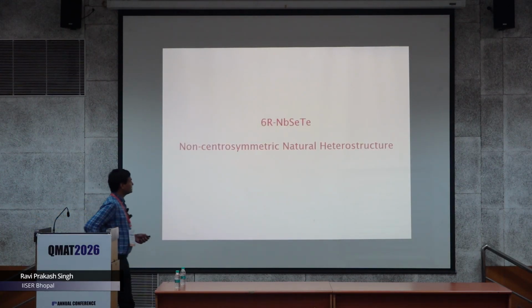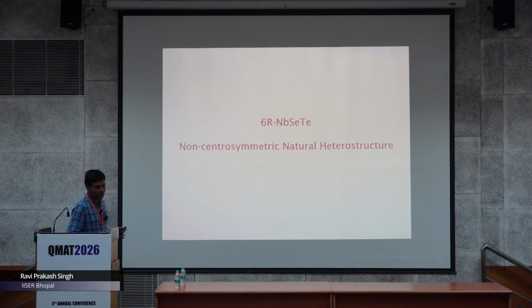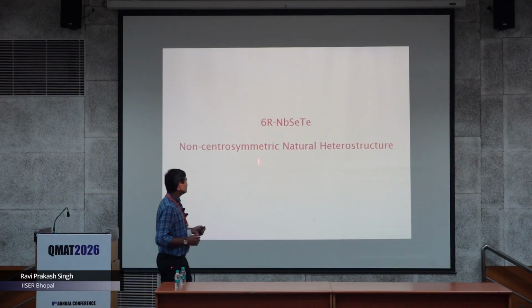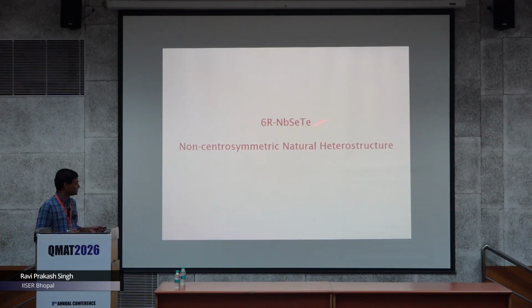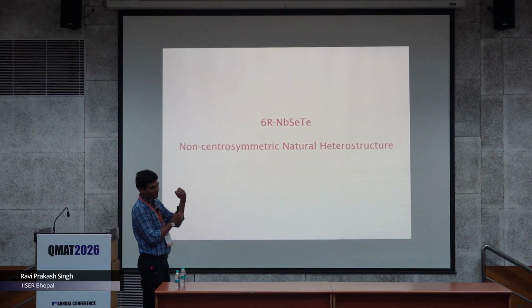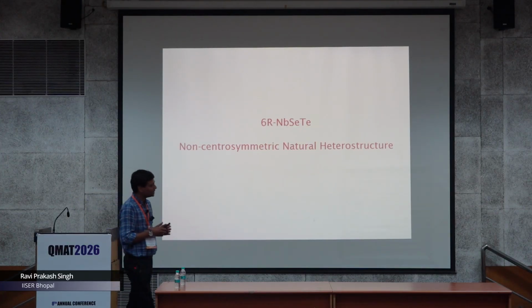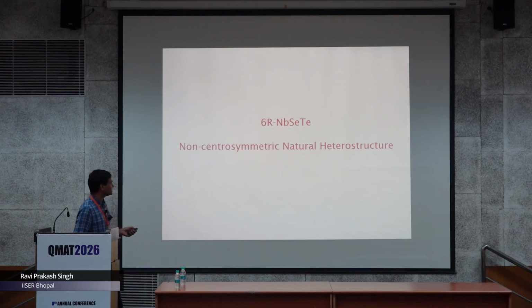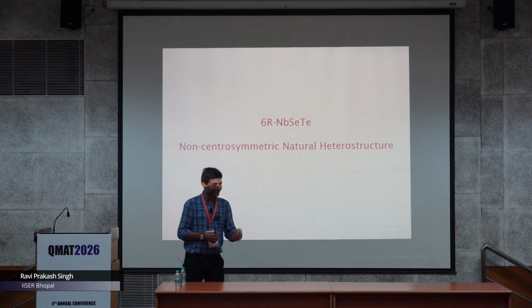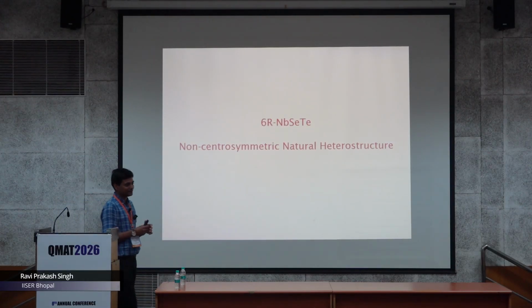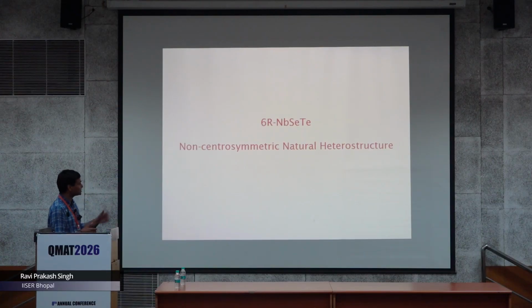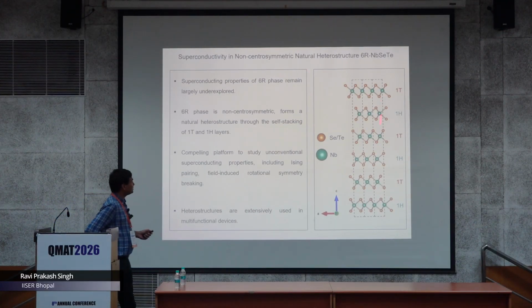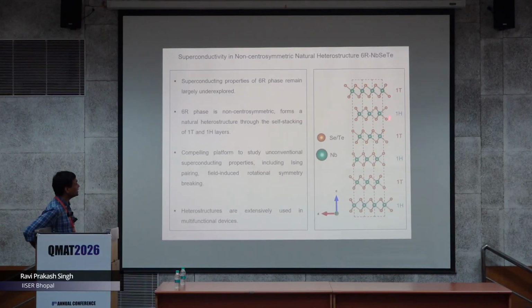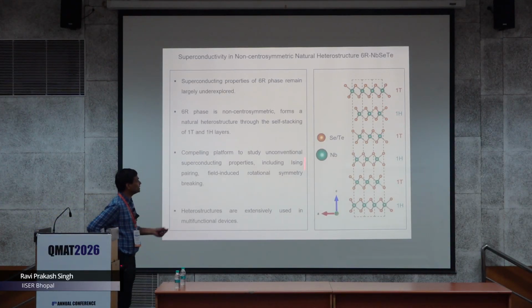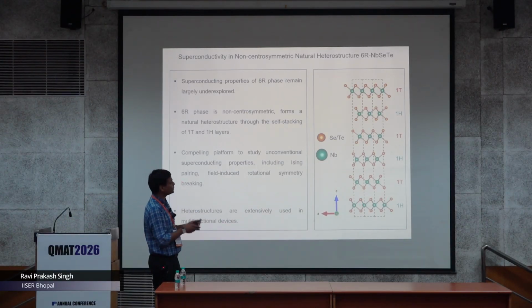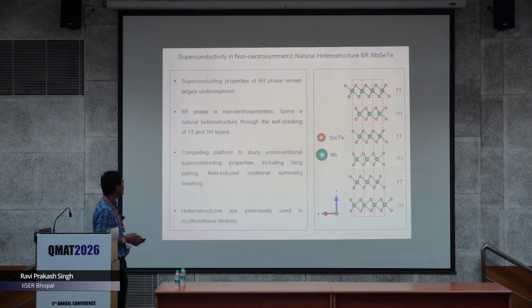So we are trying to make the 6H NbSe2 because we want to continue in that direction, but sometimes you have to add a third element to stabilize the structure. So we tried with that and we ended up with 6R NbSeTe, and I realize already it is work by Sanjay, mostly the charge density wave and the structural analysis. So it is a bit different. Here it is made of 1T and 1H layers, but the whole structure is non-centrosymmetric. So it is a natural heterostructure, we can say, of 1T and 1H.